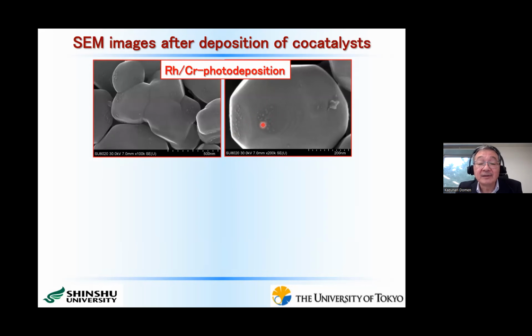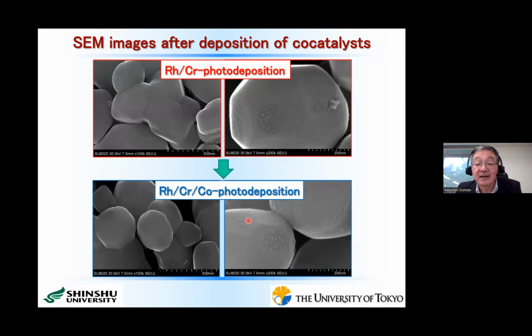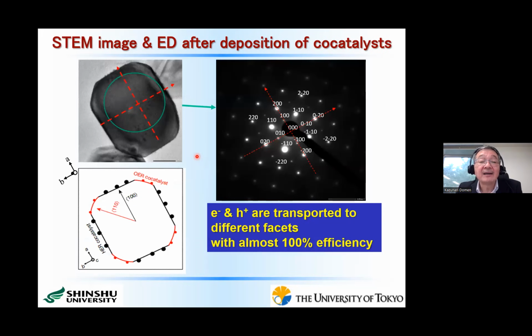However, when we introduce cobalt oxide for oxygen evolution by the photo-oxidation reaction, almost all facets contain some particles. That means that this cobalt oxide is actually deposited on different facets from the rhodium and chromium cocatalyst. To understand this situation in more detail, we carried out a high-resolution STEM measurement. This is one particle of our photocatalyst, and from this area, we took an electron diffraction pattern, as shown here. From this electron diffraction pattern, we can identify that these flat facets are the 100 facet and their family. And I hope that you can see that some small particles exist on these surfaces.